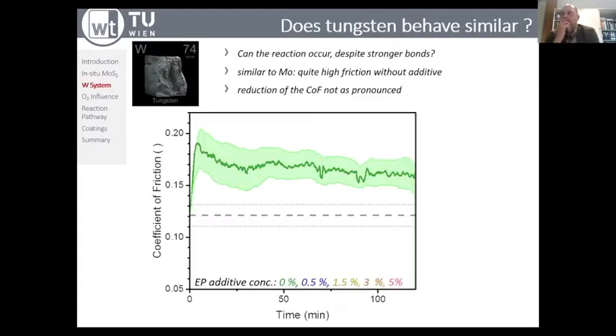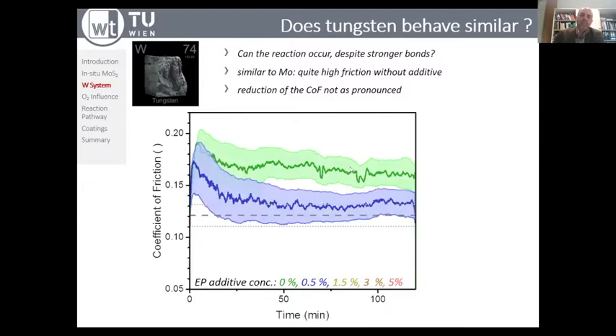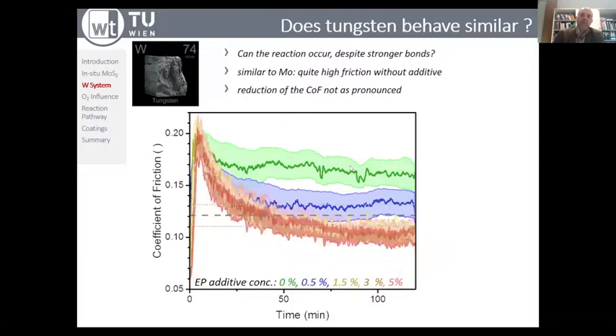Then I said before, what happens if we do the same with tungsten? Can the reaction occur, despite tungsten having stronger bonds? From the chemical side it is not as reactive. It's similar to molybdenum to some extent, but when you start adding the EP additive step by step, so 0.5, 1.5, 3%, and even 5%, there is a drop in the friction coefficient compared to the situation with no EP additive, but it was not as large as we expected. And the question was, why?